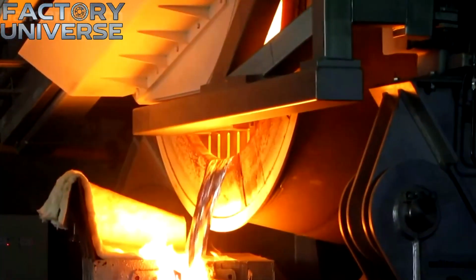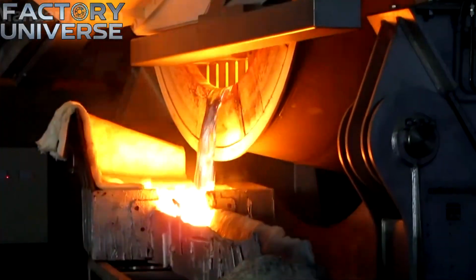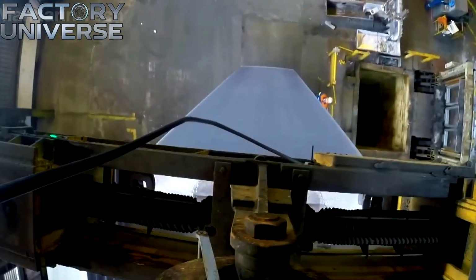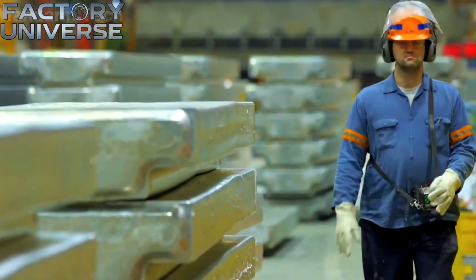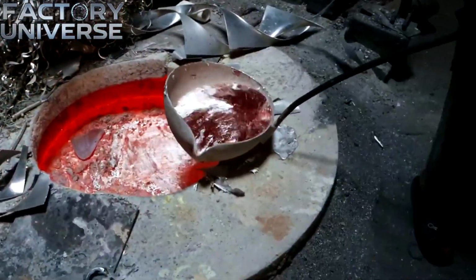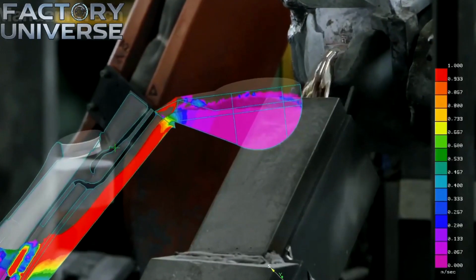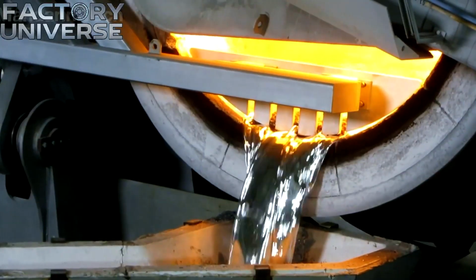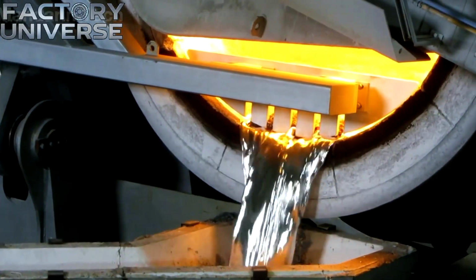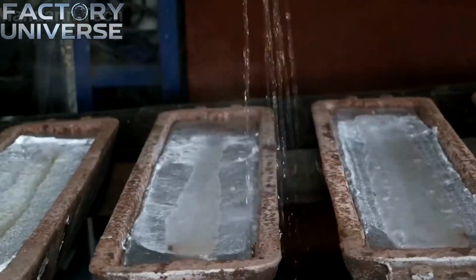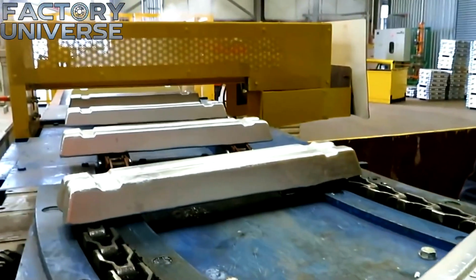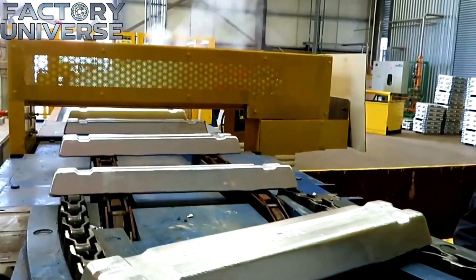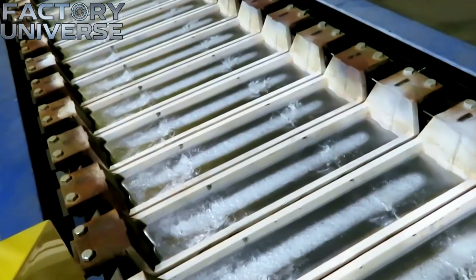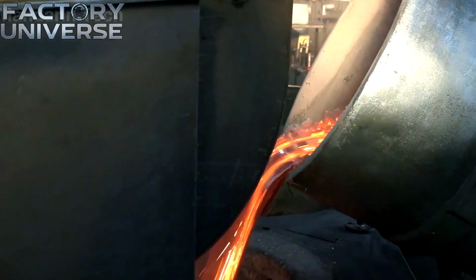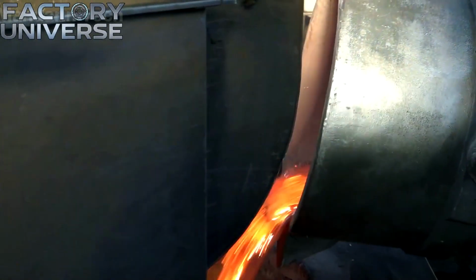The process is only gaining momentum as the molten stream fills the voids. At first glance, the flow of metal seems simple, but in reality, every variable must remain in a state of perfect balance. If the liquid aluminum flows at a speed that is too high, gas pockets or surface cracks can form within the structure. If the mold is too cold, the solidification occurs unevenly, which inevitably creates internal defects. Therefore, the operators must guide the steady stream through the narrow channels without the slightest deviation. Any small change in the flow rate can distort the entire shape of the finished piece.